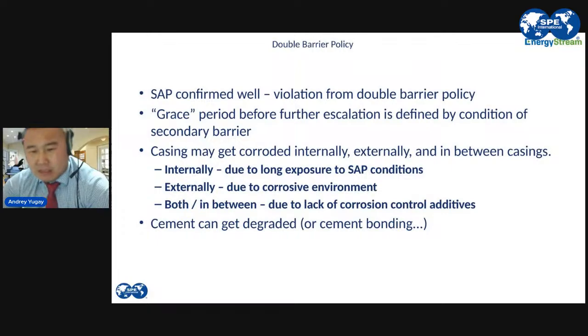Now, as I say, casing may corrode externally, internally, and in between. And there are different mitigation and prevention measures to control such secondary barrier degradation. Cement can degrade with time as well. Pressure, temperature cycles, ballooning. Every time you pressure test your casing, you damage your cement, because cement has a high compressive strength, 3,000, 4,000 psi maybe, if you're talking about the tail. But in tension, service providers normally take a value which is 10 times less than the compressive strength. And when you pressurize your casing, that's exactly what you're doing. You stress your cement ring in tension mode.